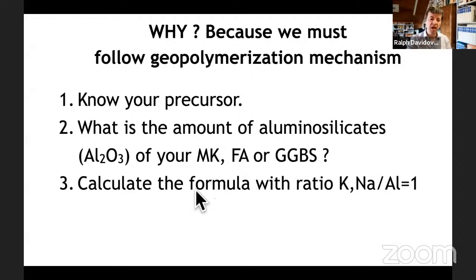Number three, calculate the formula with ratio potassium or sodium to aluminium equals 1. Once you know the amount of Al2O3, you can calculate your formula. Respecting the ratio sodium to aluminium equals 1 guarantees there will be no leachates, no blooming of free salt, no shrinkage, no cracks with enough fillers, of course. It will provide good chemical and structural stability. I repeat, because it's very important.